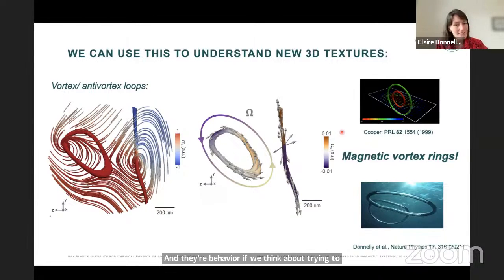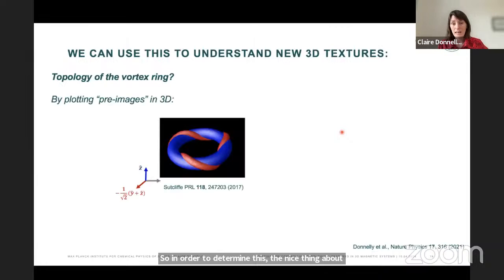But before we go on to that, what we were particularly interested in on the topic of topology was understanding why these textures were actually stable in our system, and the question of had we observed such a topologically non-trivial vortex ring. So in order to determine this, the nice thing about having the 3D data is that we can directly perform a second type of analysis, which is essentially the direct calculation of so-called pre-images. So these are isosurfaces that correspond to a certain direction of the magnetization.